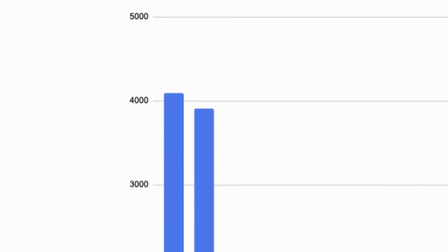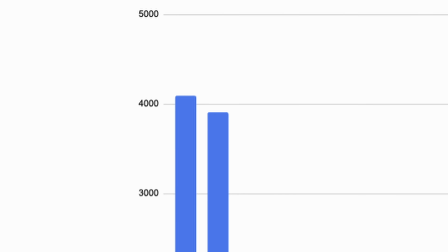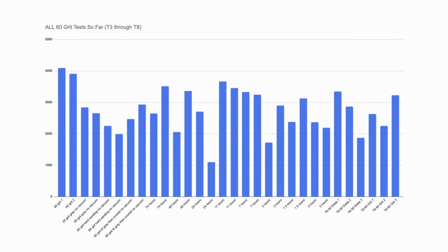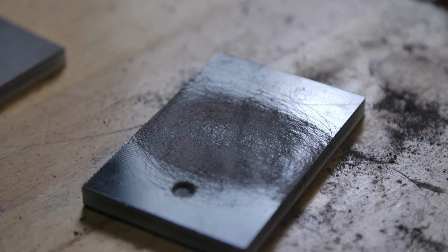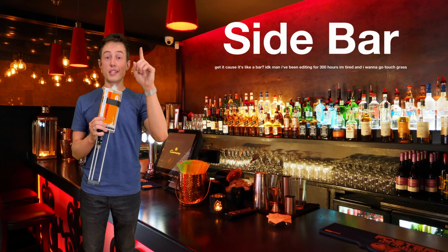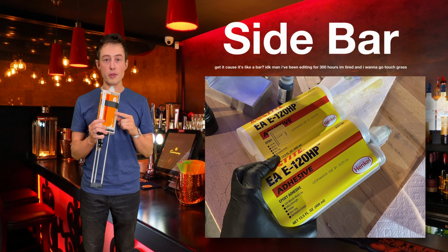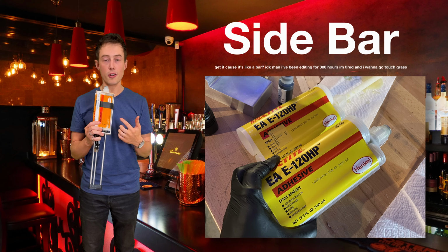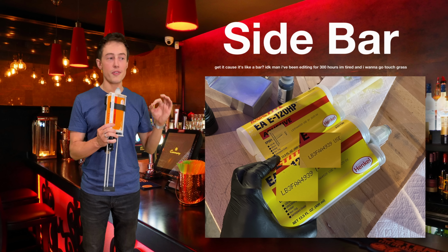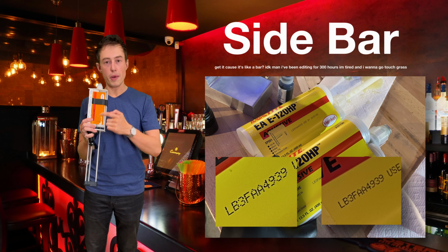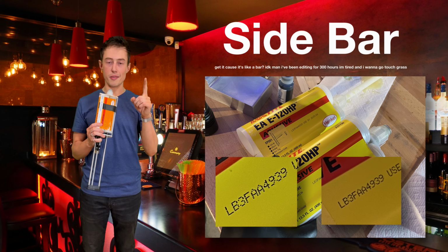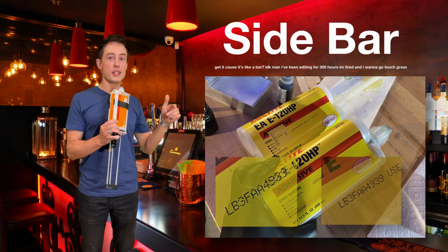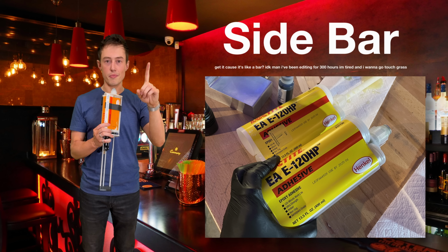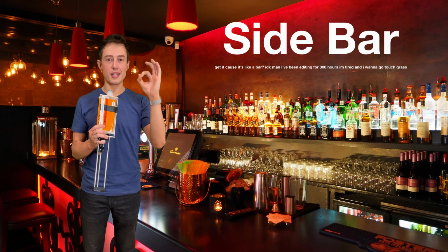That maximum strength of 4,000 newtons with 60 grit sandpaper was good, but it's clearly not replicable, at least not consistently. I must have etched it in like the perfect way, or used like the best possible batch of Loctite. Oh shoot, okay, hold on one sec. All the epoxy is from the same batch. It's all Loctite E120 HP, and although I switched to a bunch of different cartridges, I purchased a large order of this stuff at the very start and ensured that the label for the batch number on each cartridge was exactly the same. So even though the cartridges are different, the Loctite batch number is exactly the same. So it's probably as close as I can get to maintaining batch consistency.